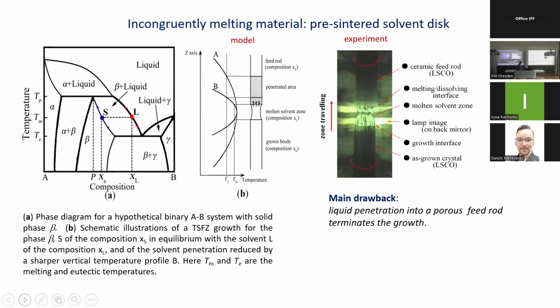And so if your material melts below 1000 degrees, then you are not able to prepare a high density feed rod, and so we could not apply this technique for the growth, for example, of YBCO materials. Also, penetration length depends on the temperature gradient at the edge of the molten zone. A higher temperature gradient reduces the penetration length.